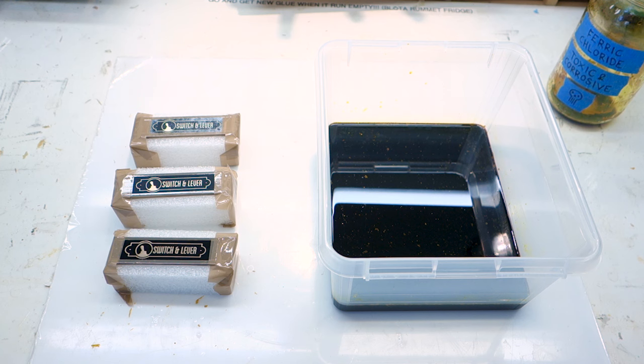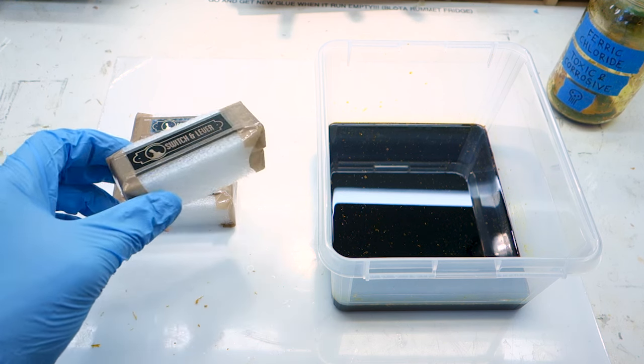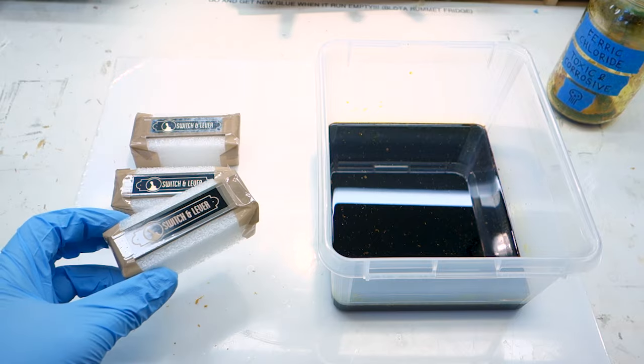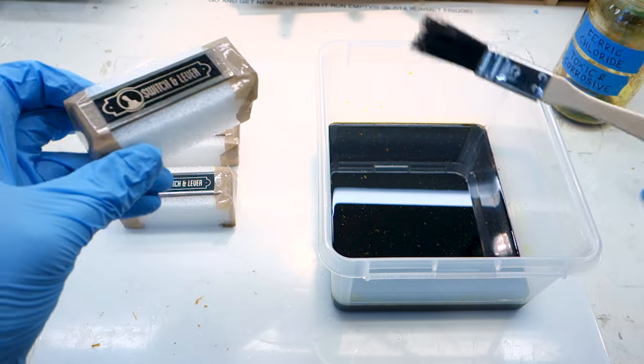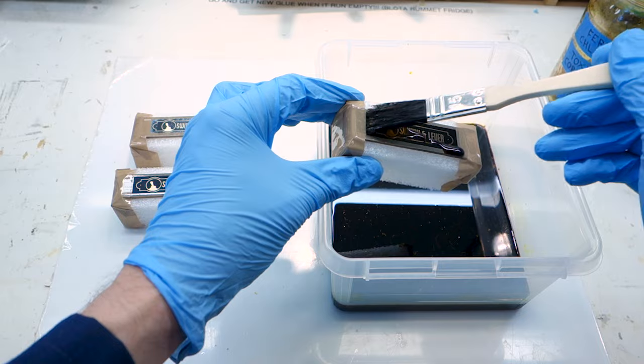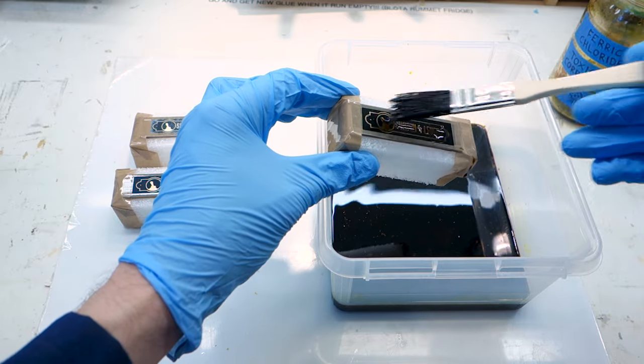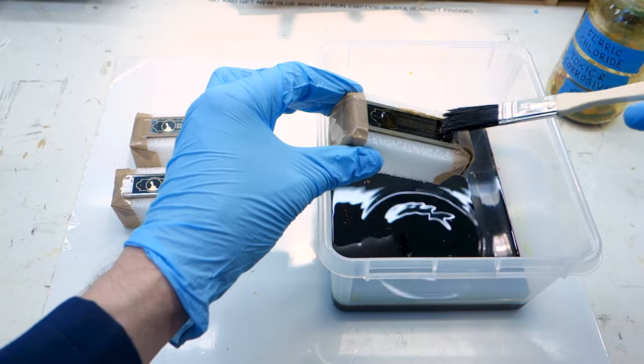Finally the moment we've been waiting for, let's let the brass meet the acid and make magic! I poured out my ferric chloride in a wider plastic box to have space for all three of my plaques. I also started by brushing some ferric chloride on the plaques being etched to make sure the acid contacts all parts which will be etched and removes the chance for air bubbles which will prevent the etchant from doing its job.